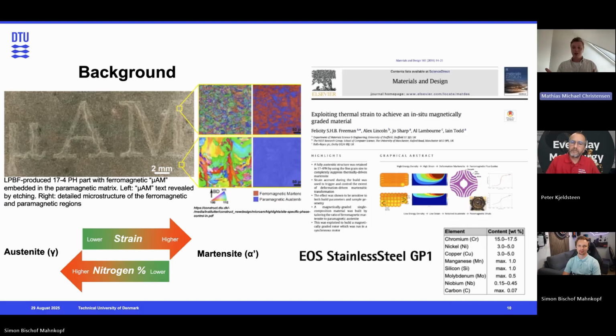So EOS, I think, realized that their GP1 powder, which was nitrogen atomized, was promoting austenite, and getting an austenite print when you have a martensitic stainless steel is a little bit off-putting. So they moved over to argon atomizing the powder. So we have our little old vintage stock of old powder that we're hoarding, almost like a wine collector, because we can use this to create unique geometry, or to create this unique phenomenon, which you can't do when you're using just argon atomized powder, or at least it becomes a little bit more difficult. And that's simply due to the nitrogen promoting the austenite phase more than the martensitic phase.